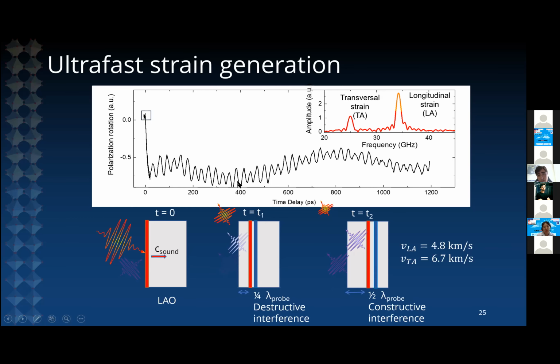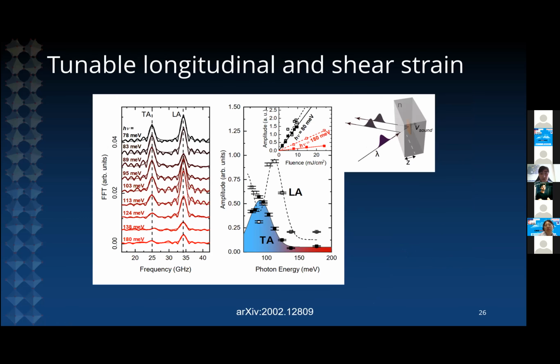And through this pattern of oscillations, we can extract the velocity of this propagating front, which matches precisely the longitudinal speed of sound of the material, so 4.8 kilometers per second. So in addition to this longitudinal strain wave, we also observe a second peak in the Fourier transform that corresponds to a propagating velocity of a strain front of the order of 6.7 kilometers per second, which is characteristic of the transverse strain of the material. So the transverse acoustic mode has precisely this speed. So this means that in addition to an expansion of the lattice parameter, we also observe a B over A type of distortion of the system, which is a shear strain wave.